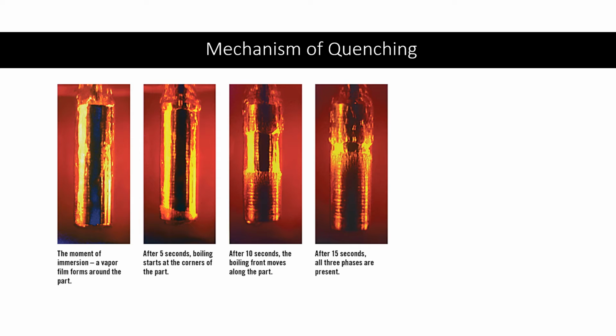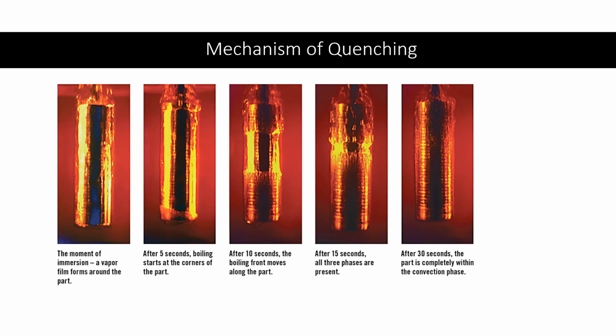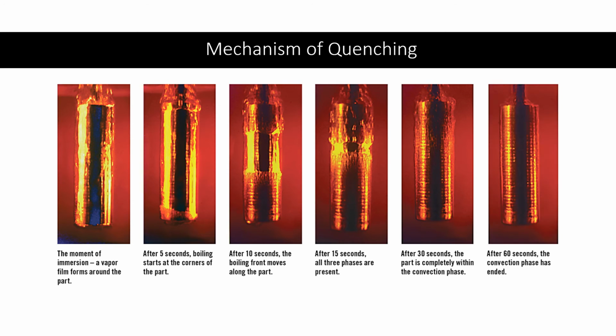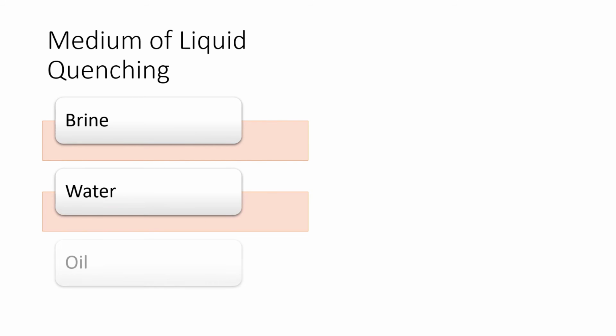Some part of the object starts to cool down. After 30 seconds, the part is nearly at the end of the convection phase. And after a minute, the convection phase ended. It can be observed that the three phases of quenching can occur simultaneously on the part. As I have mentioned previously in the lecture video, there are three mediums of quenching in heat treatment of steels, and these are brine, water, and oil.